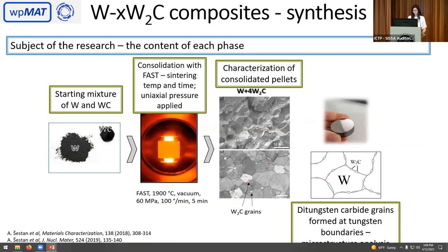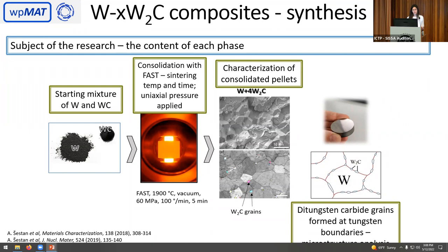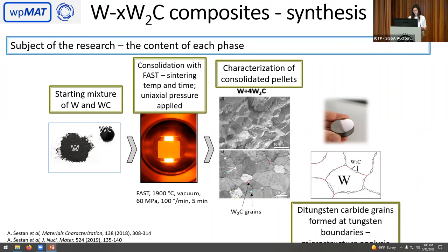The research at the institute — what the nanomaterials department does — starts with a mixture of tungsten and tungsten carbide, which is the latter of the two approaches I suggested. It uses fast sintering to make the pellets and includes variables like sintering temperature, time, and the uniaxial pressure applied. The output is the consolidated pellets, and you can see the microstructure showing ditungsten carbide grains formed in the tungsten boundaries.